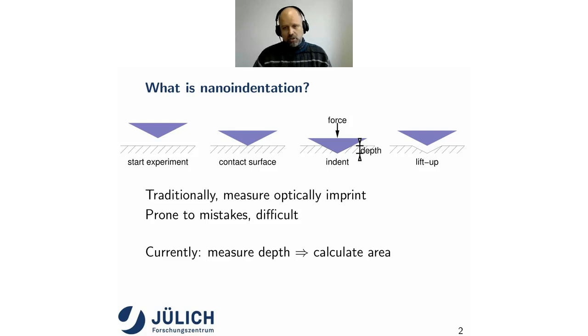Traditionally we do that optically, where after the indent, we look from the top optically, and that's why the Vickers indenter has been so important, because it's easy to identify the corners with the Vickers indenter. But that was very prone to mistakes and difficult, so currently everything is measured by depth. So you measure the depth of the indent during the indentation, and from that you back calculate the contact area.